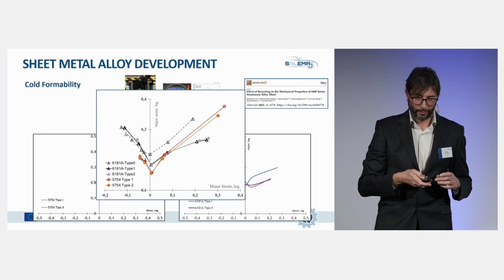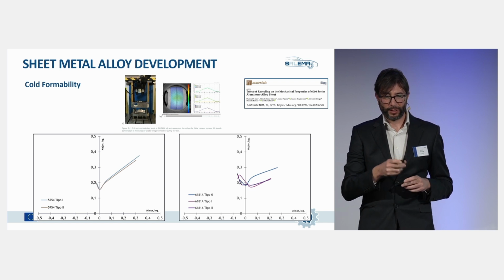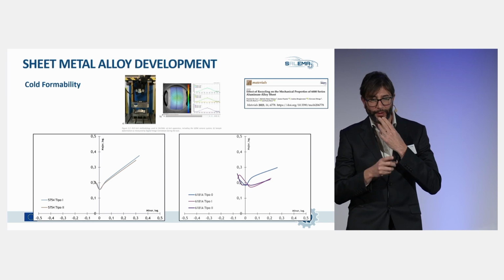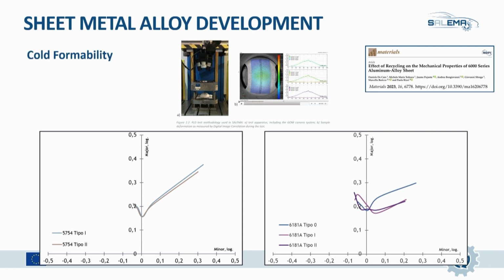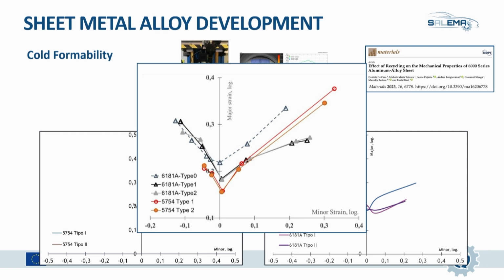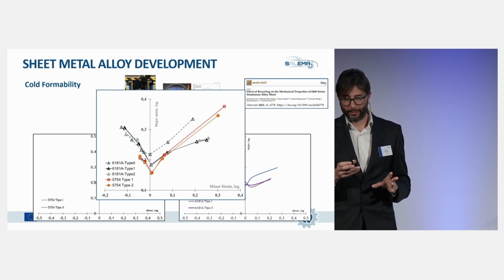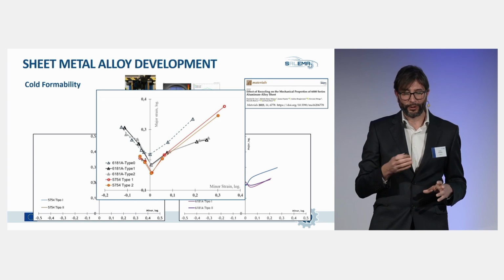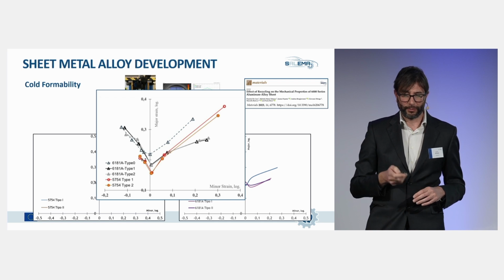We also wanted to measure the formability, the FLC curve, and we observed that in the 5754, almost both curves fit, with no loss in formability, but in the 6181, there was a change in the alloy formability. But if we put all these curves together, we see that even in the 6181, we are losing some formability. The new formability is more or less at the level of the 5000 alloys. It's not that big a loss, so the formability is still quite good. And so we were pretty happy and sure that these alloys could also be used to form complex shape components by stamping.